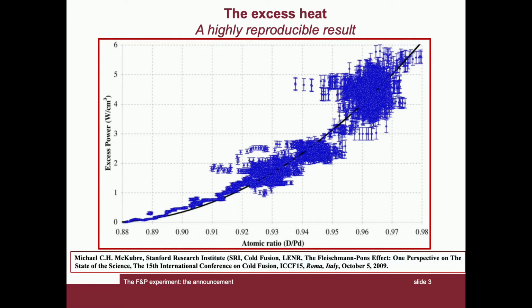The excess heat. The most significant evidence of the experiments performed over the years on the model of those of Fleischmann and Pons is that the excess power measured increases as a function of the deuterium-palladium ratio in the cathodes of the various electrolysis cells tested. The data are substantially connected in a curve that grows almost exponentially. It should be noted that the graph shows thousands of experimental data obtained in different laboratories around the world, not always obtained following the same experimental methods as Fleischmann and Pons. Note that the curve has further enriched with consistent data over the years.